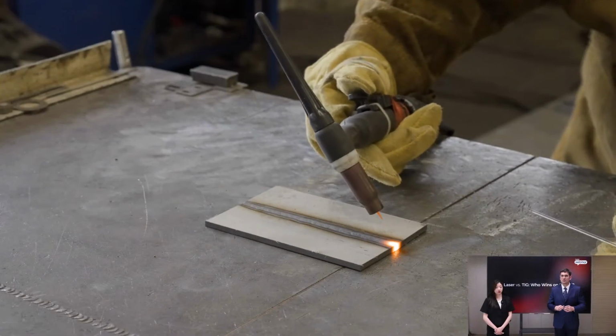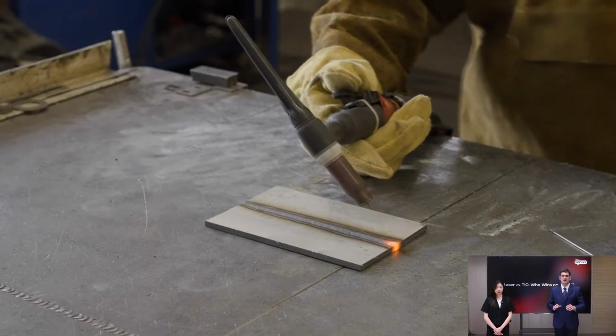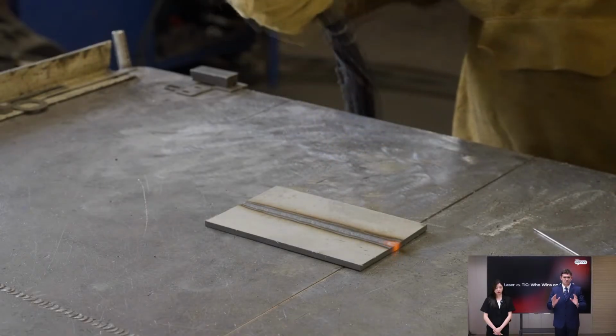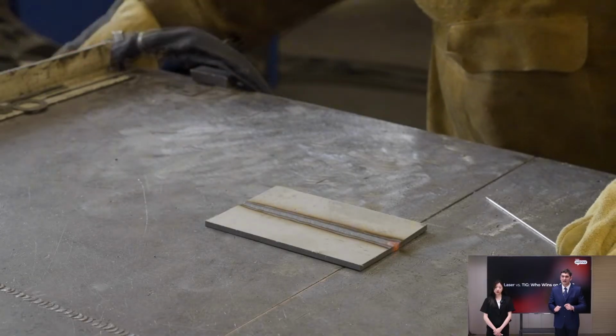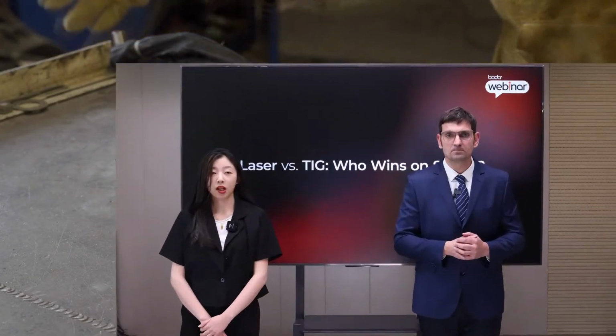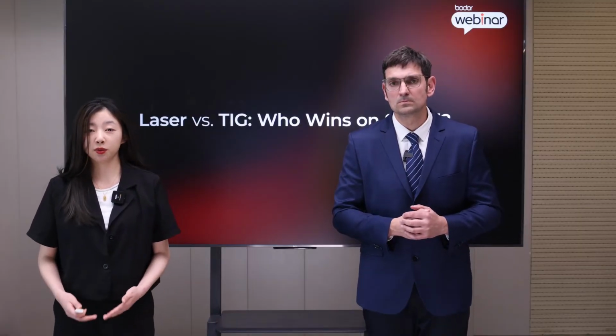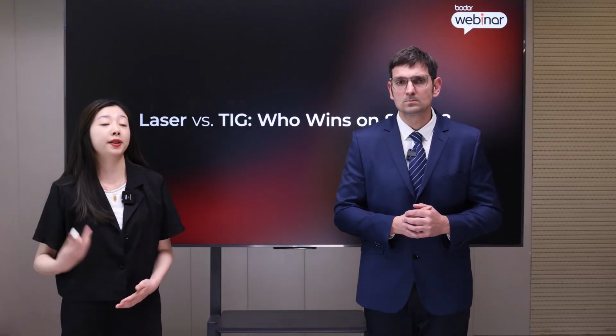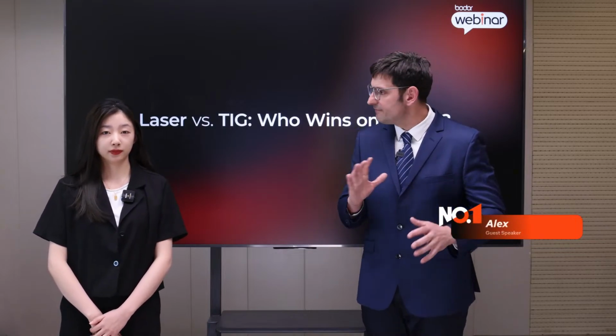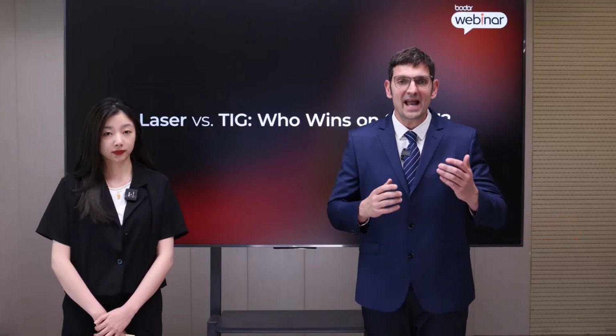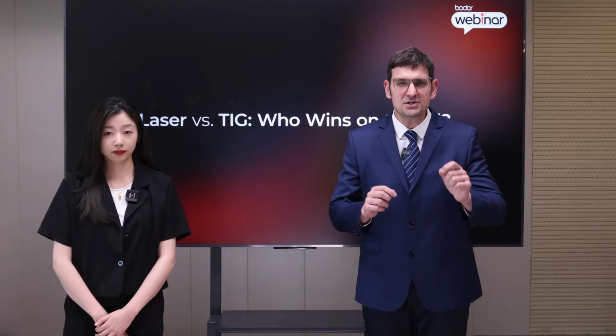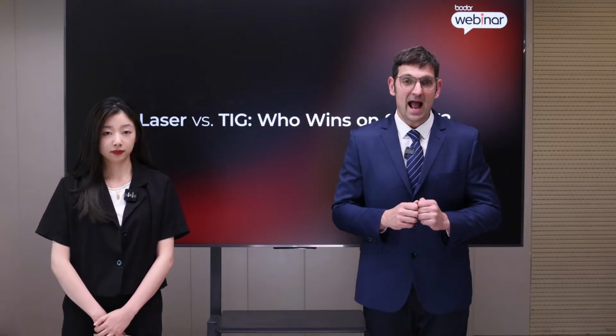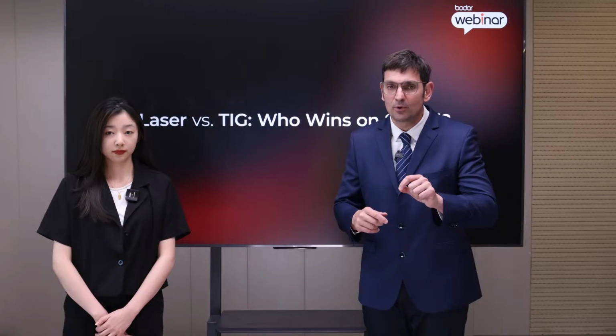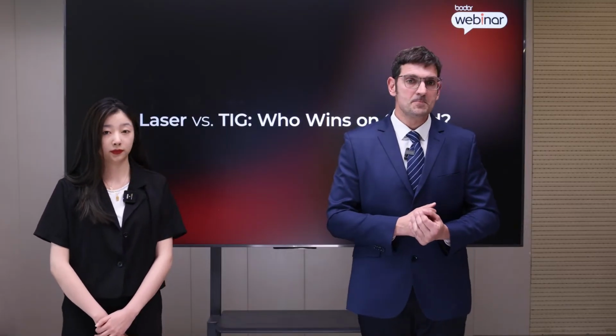The workpieces welded with TIG have a large thermal effect, slow heat dissipation, and are extremely hot to touch. We need to wait for the heat to dissipate. It looks like there's some warping on the TIG workpiece. That's a common issue with TIG, mainly because of its wider heat-affected zone. The surrounding metal absorbs more heat, which can cause edge lift and distortion, especially on thinner materials. And the thinner the plate, the more noticeable that warping becomes.